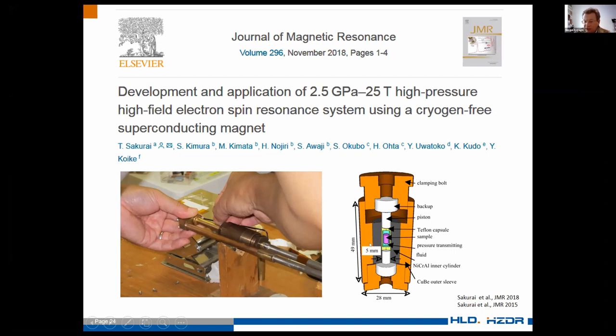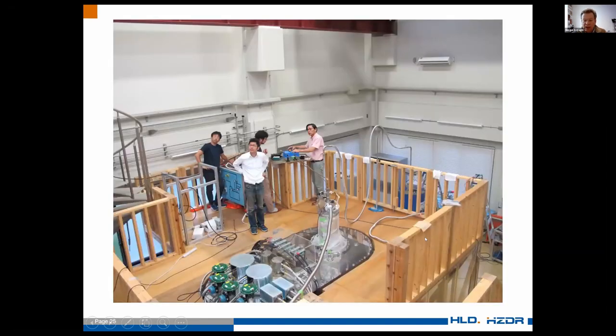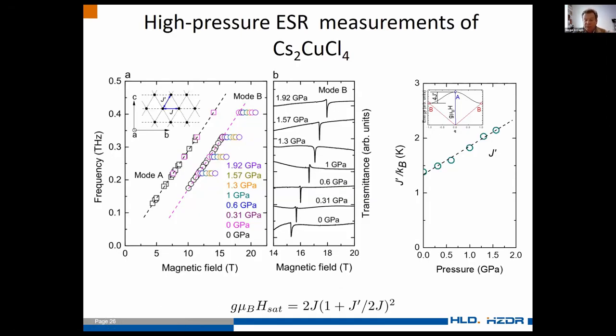What is quite interesting is that these parts are made from zirconia ceramic, and this material appears to be very good for microwave transmission. It attenuates, but not so much. Radiation comes from here, this is the sample, and this is the pressure cell. We did high pressure ESR up to 2 GPa, and you can see that once you start applying pressure, this line gets shifted. This is very nice because the shift of these exchange modes tells us how J prime changes as a function of pressure.